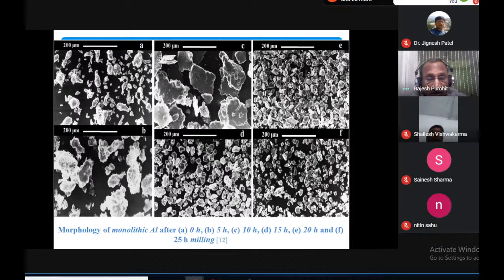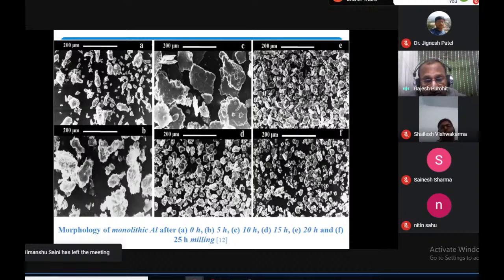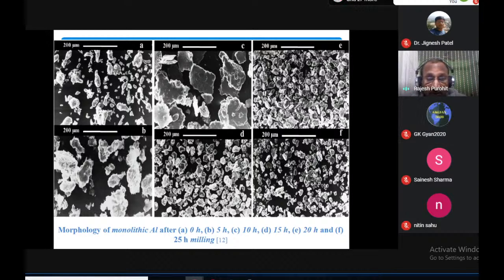It is basically mechanical alloying, using the ball mill. In a ball mill there are balls in a cylindrical container, and generally we fill up to about 10 to 15 percent powder material. So we take aluminum in powder form and alumina also in powder form and run the ball mill for maybe 10 hours or 15 or 20 hours.